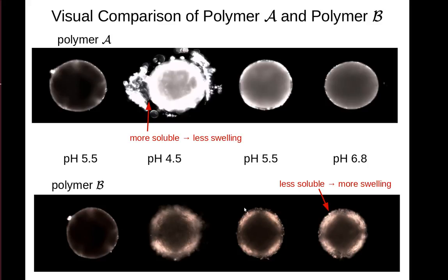We can compare these two polymers again with the formulation itself. On the top, Polymer A, again we have the core, and then the three pHs, 4.5, 5.5, 6.8. And below, Polymer B, same pHs. And what we'll see is that at 4.5, both of them are fairly soluble, same with 5.5. The most interesting thing probably comes between 5.5 of Polymer A, where it's between its two extremes of rapid dissolution and no dissolution. And for Polymer B, that difference occurs more at around 6.8, where there's not rapid dissolution, but there is some during the course of the experiment. Remember that Polymer B is much less soluble, and therefore it will probably undergo much more swelling.